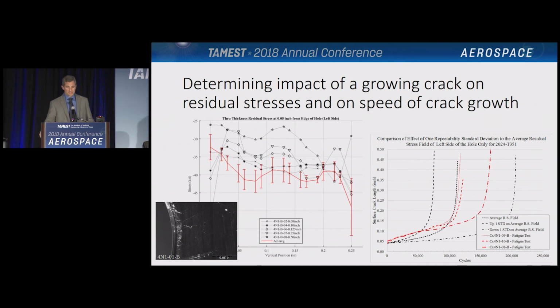And as the crack grows, the different black lines above it show that the stresses decrease as the crack grows to an average of about negative 30 KSI for a half-inch crack. So incorporating these different stresses into our fracture models at the different crack lengths allows us to determine what the crack growth lives might look like.